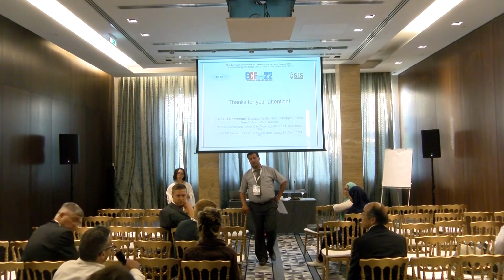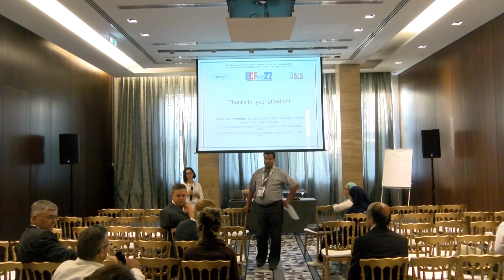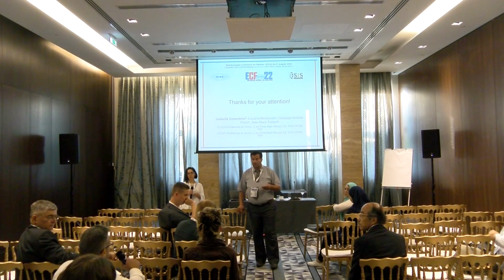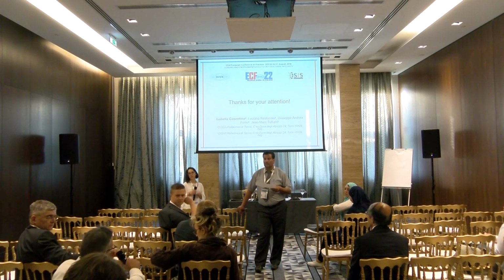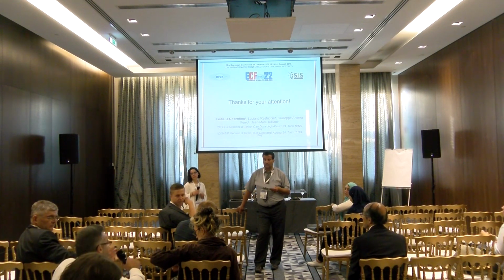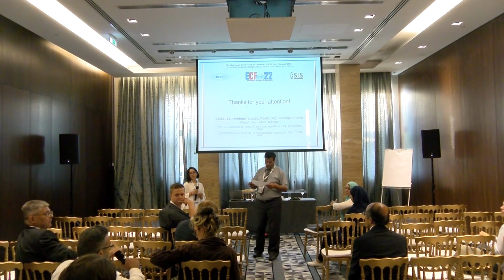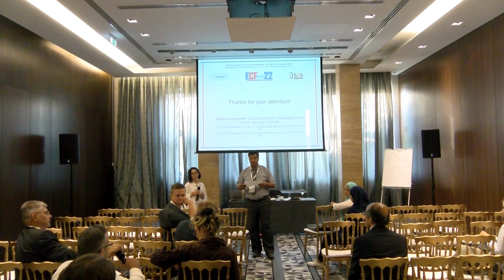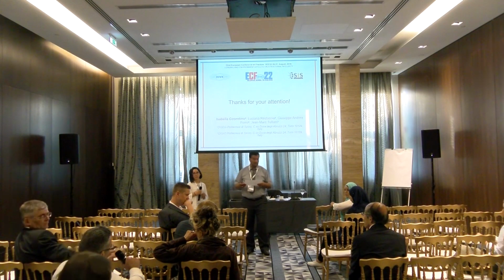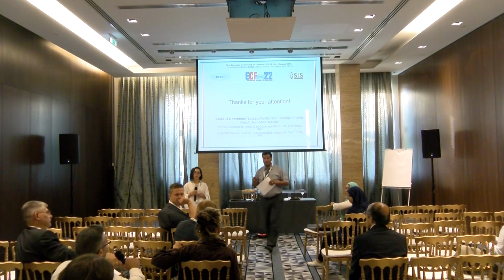I have to confess that for 2024, the previous alloy that I presented, it's already mature, that is hydrogen brittled. For 2198, I still don't know any publications dealing with this subject. And how do you measure hydrogen? Of course, you can measure it with thermal desorption and some concentrations in ppm, but this is something the laboratory of mechanics cannot perform just like this. So we simply take the mechanistic approach, measuring the mechanical properties. And that's the way Christina performs low exposure time, only 2 hours, just to avoid pitting and to see the excess of ductility decrease caused by hydrogen embrittlement.